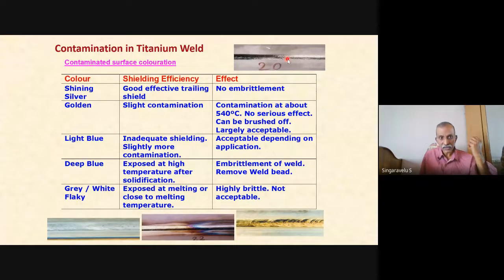The color becomes shiny silver: you have a good, effective trailing shield. No embrittlement will occur. The color becomes gold, like this: slight contamination is there, right? And it becomes light blue: it is inadequate shielding, slightly more contamination. Depending upon the application, we can decide on that. Deep blue: embrittlement of the weld, you have to remove it totally. Gray, white: highly brittle. You should not use these.